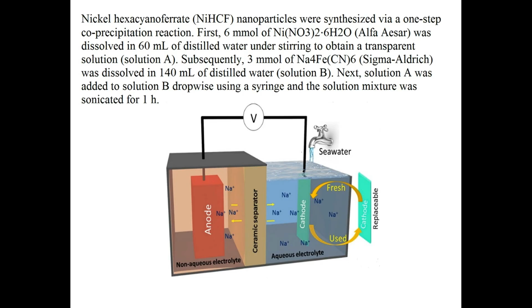First, 6 mmol of Ni(NO3)2·6H2O, Alfa Aesar, was dissolved in 60 ml of distilled water under stirring to obtain a transparent solution, solution A. Subsequently, 3 mmol of Na4Fe(CN)6, Sigma Aldrich, was dissolved in 140 ml of distilled water, solution B. Next, solution A was added to solution B dropwise using a syringe and the solution mixture was sonicated for 1 h.